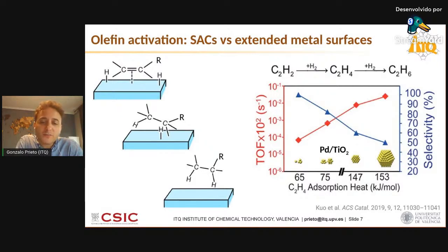It is quite well known, and has been reported here on the right hand side, showing an example based on a palladium catalyst, that the lack of direct metal-metal coordination, and let alone extended metal surfaces such as those which might be present in clusters and especially nanoparticles, inhibits the olefin pi coordination to the metal. That, as I show here on the left-hand side, is a sort of prerequisite for olefin hydrogenation reactions catalyzed by metals. Indeed, single atom catalysts are known to show outstanding up to full selectivity in alkyne semi-hydrogenation processes, selectivity to the alkene intermediate product by inhibiting very effectively further hydrogenation to the alkane side product.